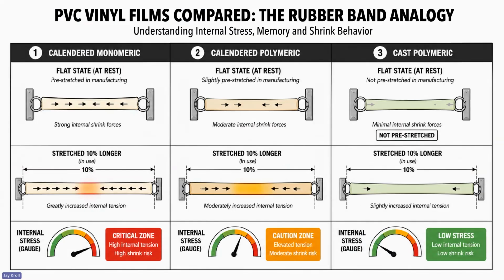Now, when we apply some stress to it, when we take that calendared monomeric and we add just 10% stretch, we see that in this example, it gets critical as far as the amount of tension that's wanting to snap back, like that rubber band that's pulled tight. The calendared polymeric, with just a little bit better chemistry on it, when you're stretching that extra bit, it's got a little bit more pullback. It's got a little bit more tension on it that wants to come back and pull, versus the cast that, you add 10% stretch, it's really minimal as far as the pullback forces that are going to be on that.